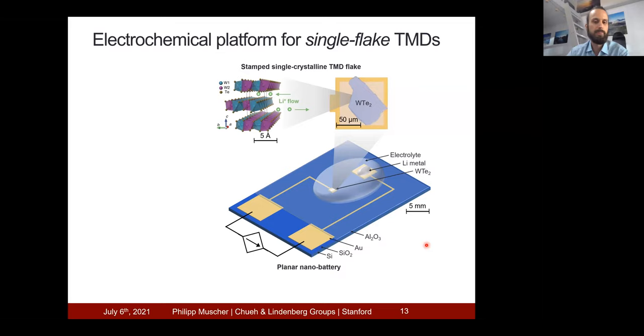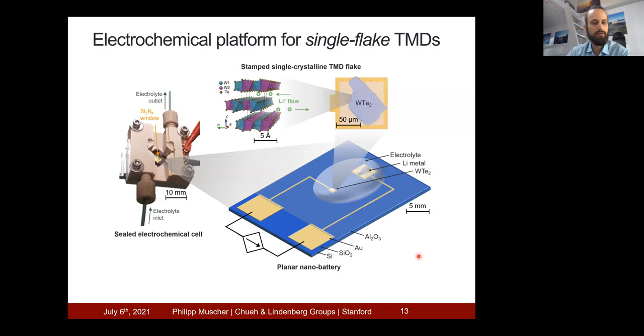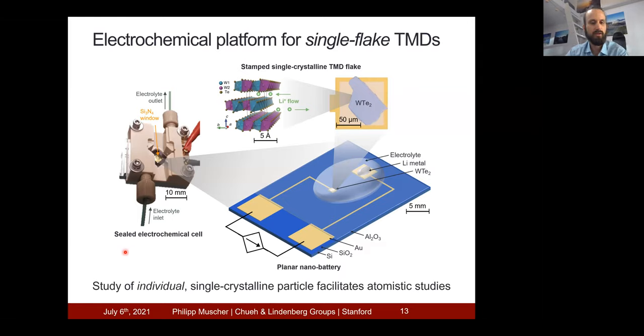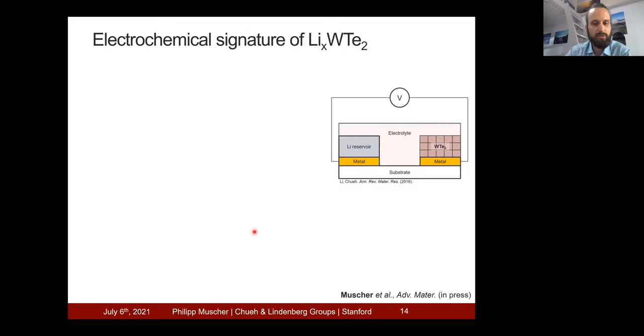Due to the use of lithium, this is highly air sensitive. And therefore, I built this sealed cell, which can house this chip. And this allows me to bring the system to all kinds of experimental setups. So this allows me to look at single flakes of tungsten ditelluride, as opposed to looking at ensembles of millions of particles. So with this platform, I can look at the electrochemical signature of tungsten ditelluride as lithium is being inserted into it.